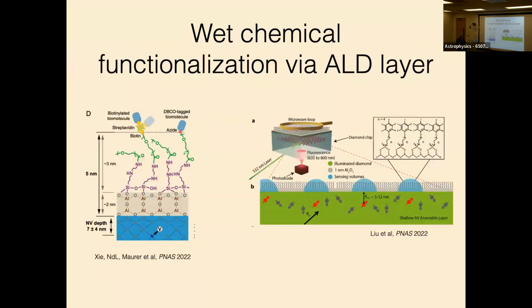So there's been some interest in this lately, and there's been a nice pair of papers that just came out this year. This was some work that we were involved in, in collaboration with Peter Maurer's group at Chicago, and it came out together with a paper from Dominic Bucher's lab, where instead of functionalizing the diamond, maybe we can just ignore the diamond and put down a functionalization layer like ALD alumina, and then use all of the beautiful chemistry that people have developed in the biophysics community to functionalize alumina. This is very nice, and it works quite well, but it comes at the cost of offsetting your NV center even further from the things that you're interested in, and we pay for distance as distance to the sixth. So this is actually a pretty big cost.